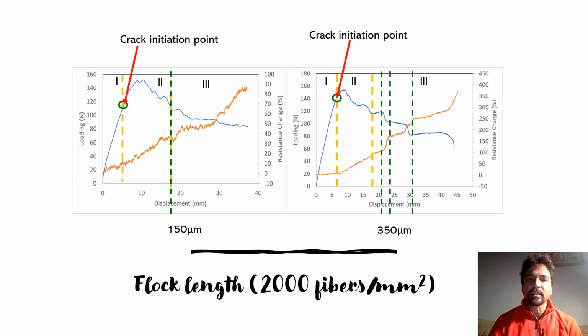As you can see in the 150 microns system, there is an increase in electrical response, but you don't see a corresponding increase in resistance for each drop in load. It's kind of gradually changing because the network is not as good as the 350 microns. However, for the system of 350 microns, those green lines are shown there to give you information about how resistance is increasing for each drop in load, where a stick-slip mechanism is happening in the system because of the bridging of the carbon fibers between the two laminates.